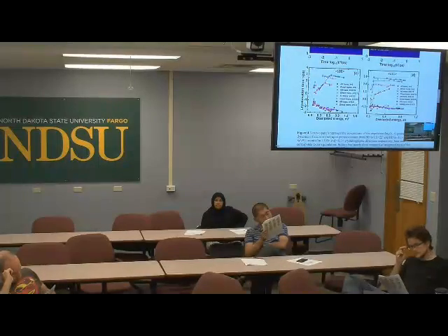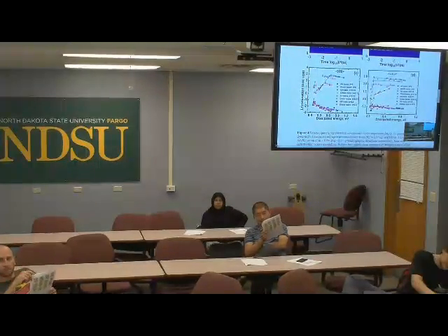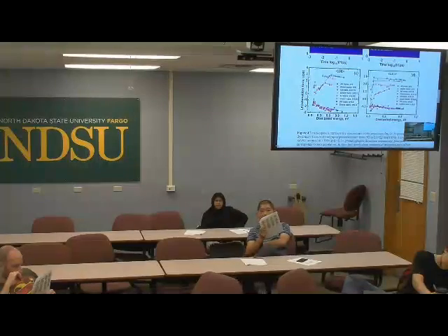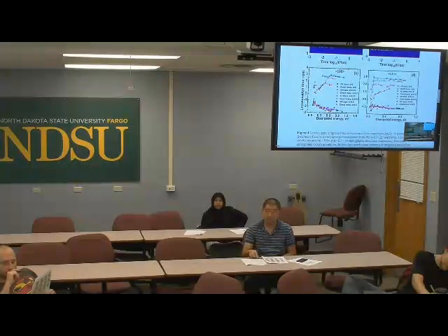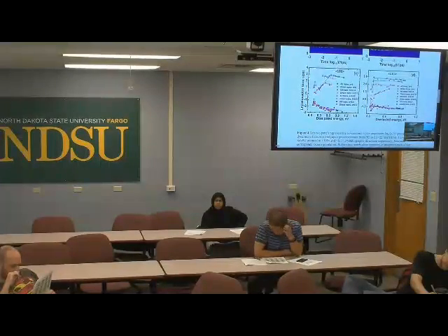Another thing: see here, the density goes along the bonding lines. It looks like a bonding orbital and it goes along the line, and it partially covers atoms. Here it doesn't cover atoms, and it is not localized on the bonding line. It's just that the charge density is localized in the space between all lines and between all atoms.